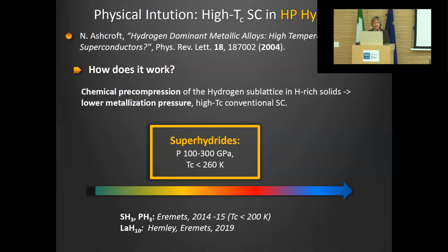And the reason is that the pressure that hydrogen needs to metallize, part of this pressure could actually be provided by the lattice, through what is called chemical precompression. The idea is that if one mixes hydrogen with some other element, and of course there is a lot of hydrogen and less of this other element, then one would have some kind of hydrogen sublattice with some atom embedded in between, and this atom would exert what is called chemical pressure, in a sense a physical pressure on the hydrogen sublattice, and thus lower the metallization pressure which is needed to make hydrogen metallic.